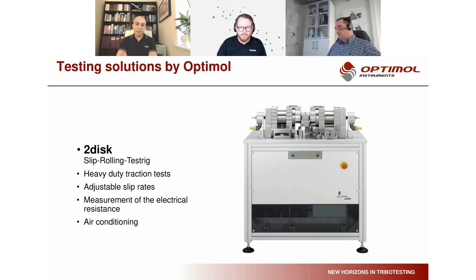Last but not least, I would like to mention with one short slide our 2-disc test rig for slip rolling testing. This is more targeting on fatigue properties. There you can do heavy-duty traction tests with adjustable slip rates, high loads up to 5 kilonewton, with plenty of measurement possibilities.